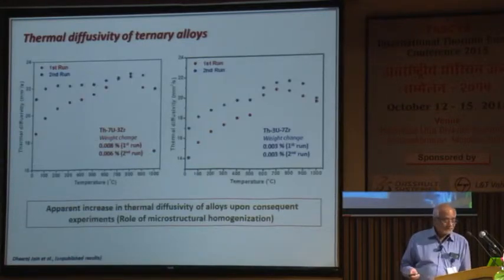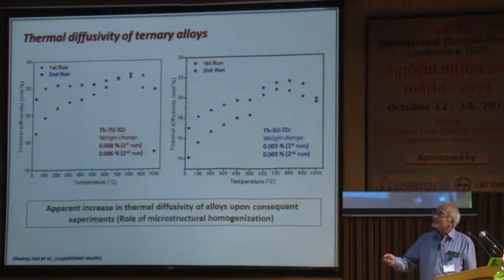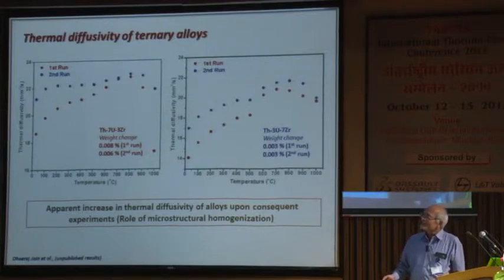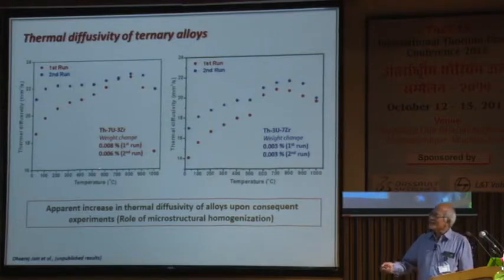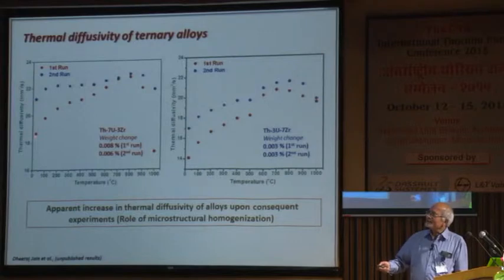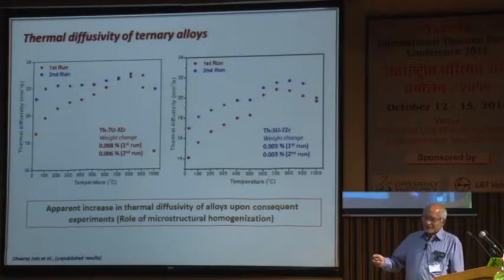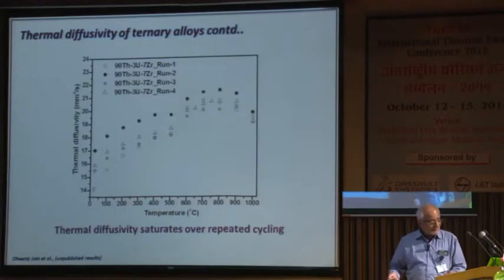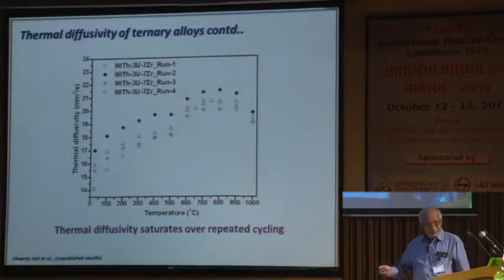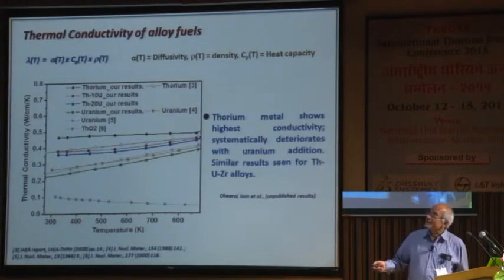And the thermal diffusivity of ternary alloys has also been investigated. This is one important thing which shows the importance of annealing of these alloys. For example, here, this is the first run, you get this data. In the second run, you start getting other data, and if you go for the third run, then it saturates. That means annealing is extremely important for such alloys.